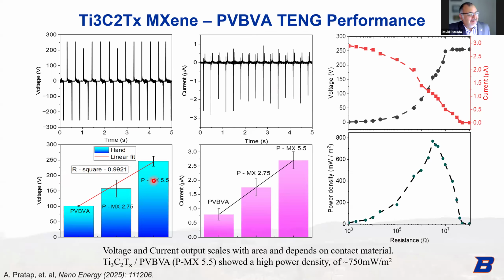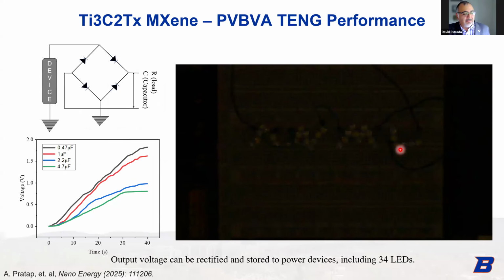Thanks, Stephanie and Joan. So yeah, we're trying to understand that solubility limit, the fundamental mechanism of that. But even within this range, you can see we're able to get over 2x increase in the voltage by the addition of MXenes to PVBVA, as well as in the current. And so this gives us a max power density of about 750 milliwatts per meter squared at a load resistance of about 10 megaohms, which is quite good compared to other TENG devices that are not using the fluoropolymers, right?